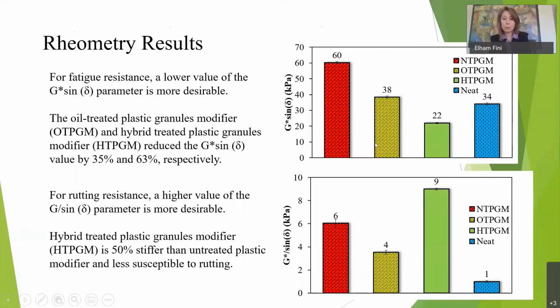So in the second picture here, you can see G star divided by sine delta, and that's a measure of rutting. You may think, what is rutting? You have seen all those sagging areas on the roads, the depressions under the traffic, where the tires pass. As the cars pass, you can see there is a bit of depth difference, a height difference on the road. That's called rutting. Of course, we don't want to have excessive rutting. It's dangerous. It can promote or cause hydroplaning. That's not good. And we want a high number in this case. So a higher value of G star over sine delta is more desirable for rutting resistance.